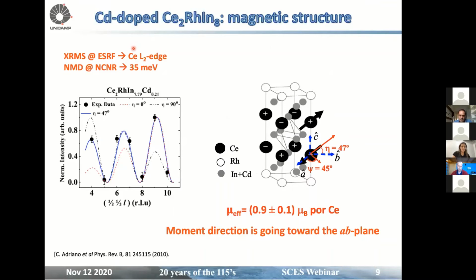At that time, we used X-ray resonant magnetic diffraction and neutron magnetic diffraction. So I'm not giving you details on the techniques. If you want, you can ask me later. But then we fit the model, and what we found for the cadmium-doped sample is that we increase the effective moment as expected for doping with cadmium, but the moment direction is going toward the ab plane.